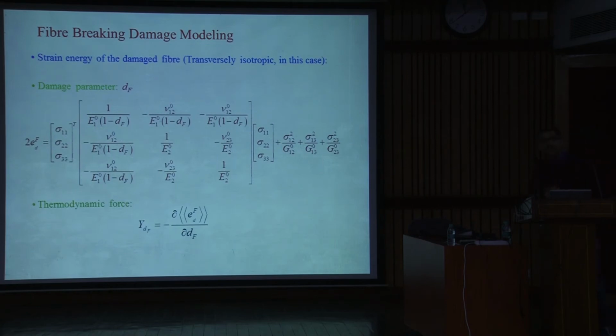Okay. So, with this, now we will do step by step how these different failure mechanisms affect your stiffness. In this development, only the key or important failure mechanisms have been considered. The first one is the fiber failure. As you know, in the composite, fiber is the main load carrying constituent. So, the majority of the load, when applied along the fiber direction, is carried by the fibers. If the fiber breaks, because it has more stiffness as compared to the matrix material, the stiffness of the lamina decreases drastically. Okay.